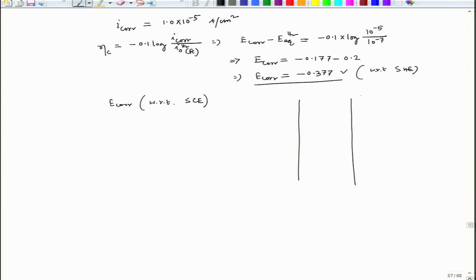we have to find out two scales. So, these are two scales. This is the standard hydrogen electrode, where this point is 0 volt, and this is the saturated calomel electrode, so the 0 point corresponds to plus 0.241 volt. This is the saturated calomel electrode, with E equilibrium equal to 0.241 volt. So, this is the standard voltage of the calomel electrode with reference to the hydrogen electrode. That will be considered as 0 when we measure any voltage with reference to the saturated calomel electrode.